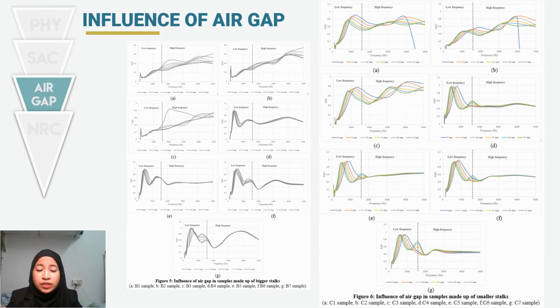For samples made up of a smaller stalk diameter, it can be seen clearly that there is no dramatic declination in figure 6a and 6b when the 5 mm of air gap is introduced to the sample. The SAC value decreased as the thickness of the air gap increased in samples C1 and C2, due to the range of difference between the values being more than 0.05. Next, we can see in figure 6C. Here we can see that the highest peak is also reduced and shifting towards low frequency with an increasing air gap.